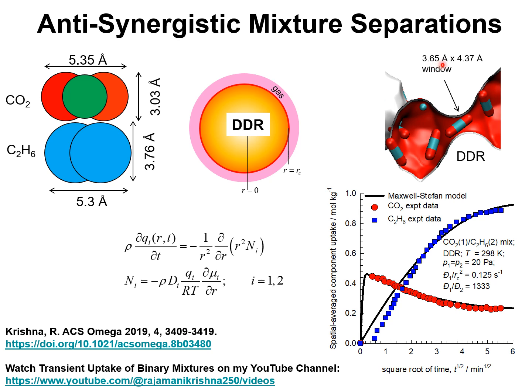The shortest aperture distance is 3.65 angstrom, and the longest distance is 4.37 angstrom. Both of these gas molecules jump lengthwise across the windows, and since the cross-sectional dimension of CO2 is smaller than that of C2H6, the mobility or diffusivity of CO2 is significantly higher than that of C2H6.